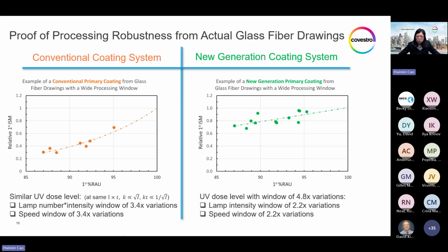The new generation coating shows a similar range too, from 87 to 95% conversion. However, in this case, it was with a much bigger processing window of UV dose level, not tuned to the same dose. It was intentionally set with 4.8 times variation, almost 5 times. And this came from a lamp intensity window of 2.2 times, and a speed window of 2.2 times. But instead of offsetting each other to the same dose level, we intentionally widened the window by having the combination of the highest speed with the lowest lamp intensity, and vice versa.